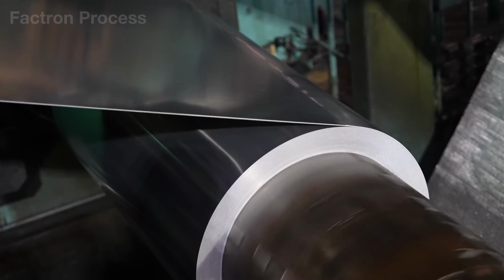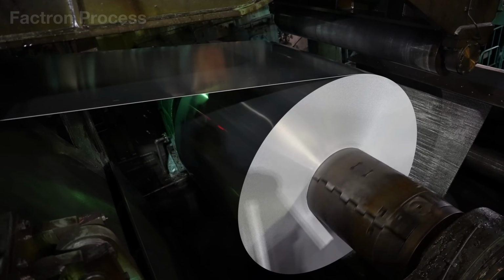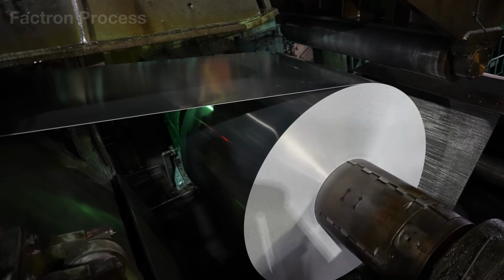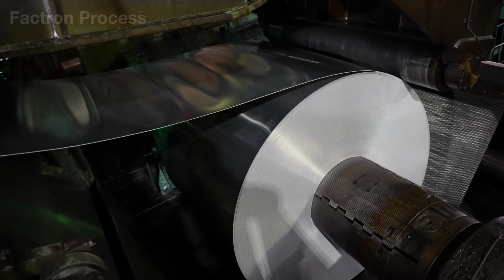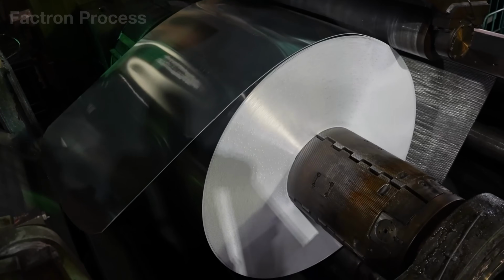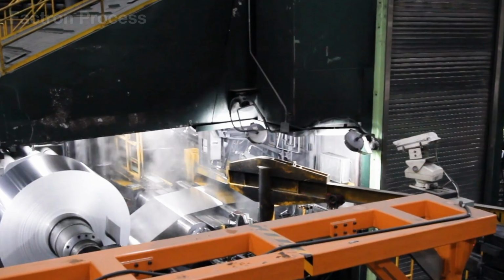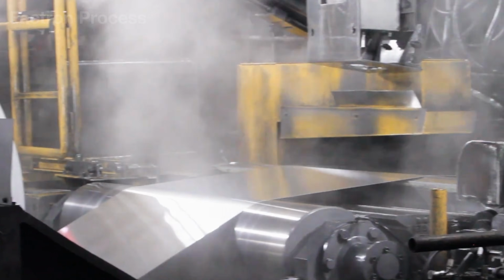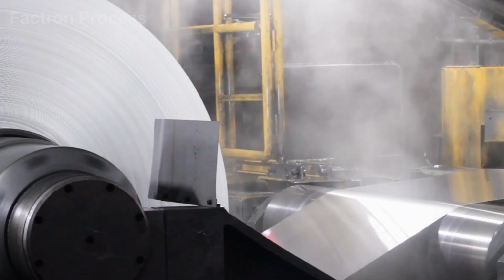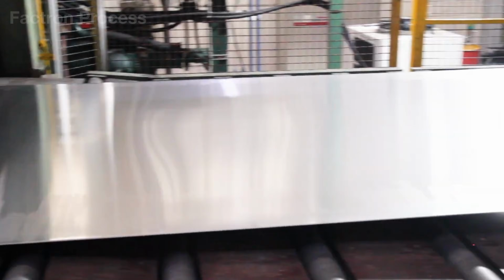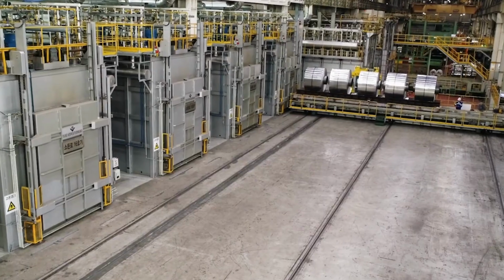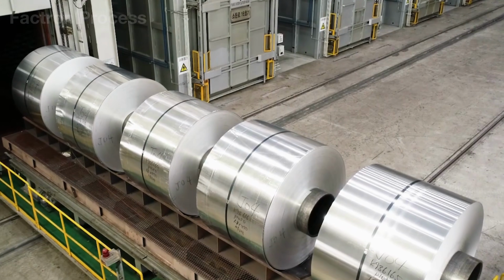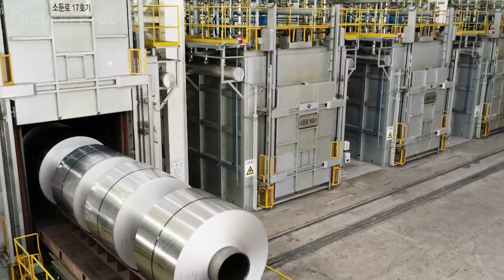From an original slab nearly 33 feet long, the finished aluminum strip can extend for approximately 6.2 miles, while its thickness is reduced to only about 0.010 inch. Sensors continuously scan the full width to measure thickness and flatness, while cameras detect scratches and circular knives trim away the uneven edges. The removed aluminum is collected and returned to the melting furnace.